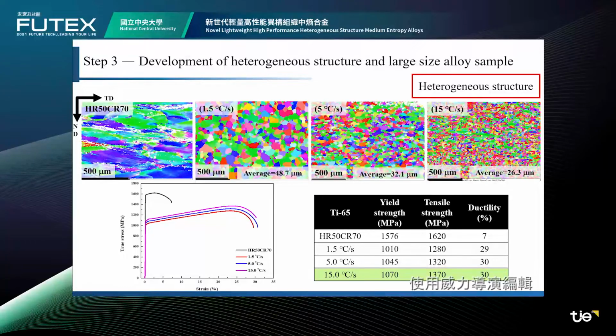In the third stage, we further discuss the parameters of thermomechanical treatment. It can be seen that the grain size of titanium 65 medium entropy alloys is effectively reduced when the heating rate of the annealing temperature increases. Corresponding to the mechanical properties, the higher the heating rate, the higher the alloy strength, which conforms to the concept of the Hall-Petch equation.